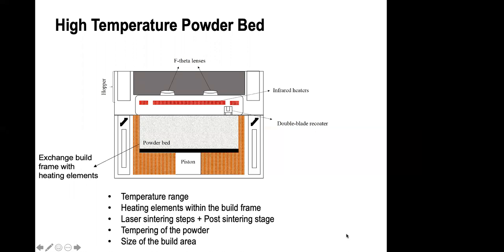Also, because the high temperature range is used, the powder bed can be more susceptible to flow changes. What we monitor at room temperature and consider a good flowing powder very often doesn't work anymore when you raise the temperature to one suitable for the process. For this reason, very often the process requires a tempering stage of the powder. During this stage, the powder is kept at elevated temperature, between 200 and 250 depending on the material, for 6 hours or more, which helps to improve the flow.